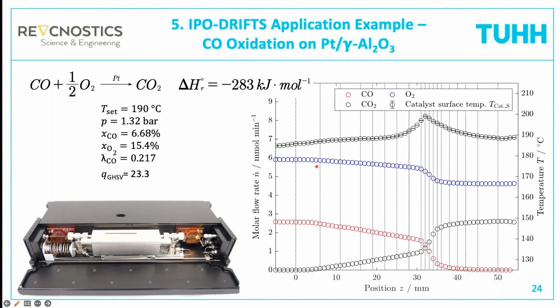And here in the right plot, you see the spatial profiles that you measure in this reactor. What you see again is 0 marks the beginning of the catalyst bed. Before the catalyst bed, there is no conversion. You see we have a horizontal line, no product. This is all good. And then when the reaction mixture hits the catalyst bed, you see how the CO is slowly converted. And you see this is almost a straight line. So we have a constant conversion rate. And here we have the conversion of oxygen, and we have here the corresponding production of CO2.